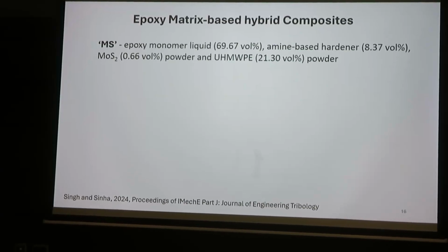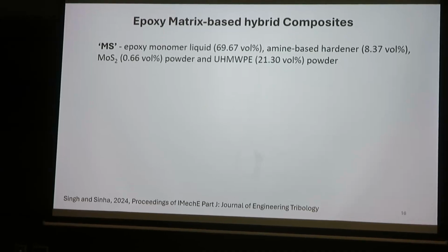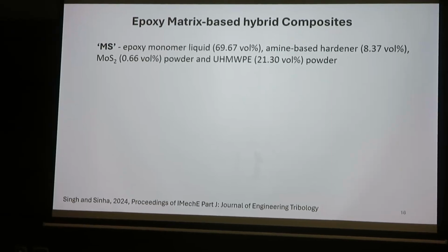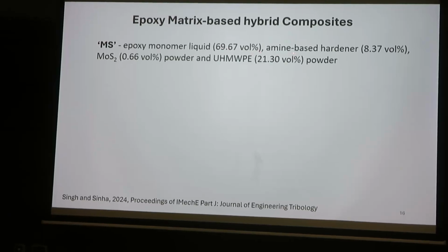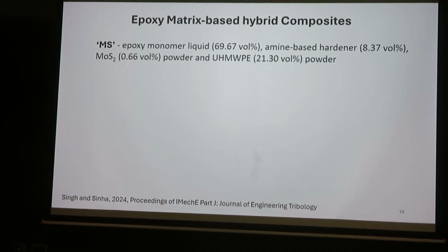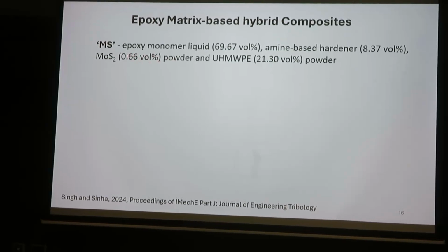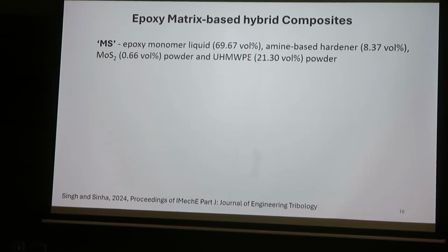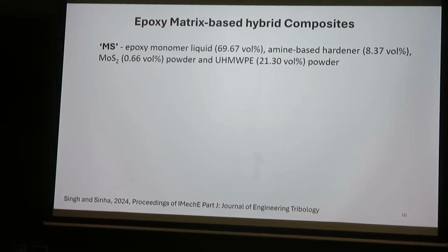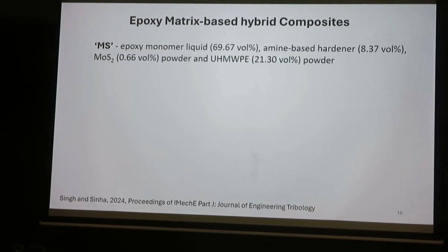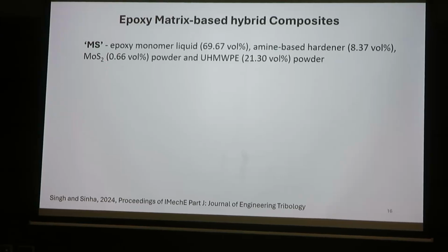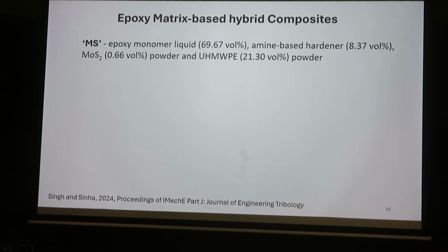In the next part, I will show you some of the composites that we made, and we have tested them for various load and speed conditions. So we made 3 types of polymer composites. All were epoxy based, basically because it's a thermoset. Normally it has good thermal properties. So epoxy with hardeners, and the fillers were MoS2. Here it is volume percentage, that's why this number is a little bit strange. And UHMWPE particles. So here we have used UHMWPE as a solid lubricant. MoS2 also is a solid lubricant, but MoS2 has some other effects also. It can harden the material, it can make the bulk better.